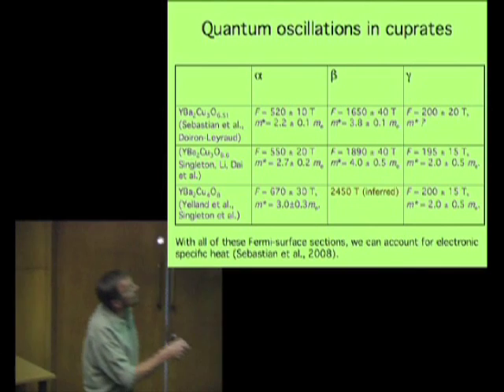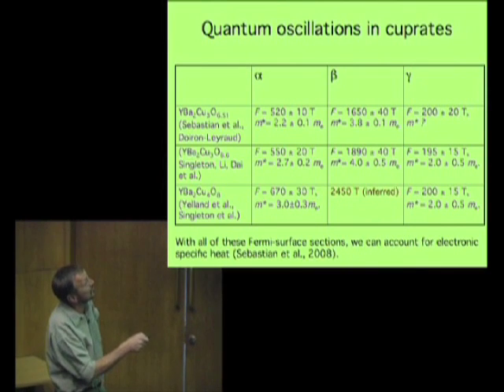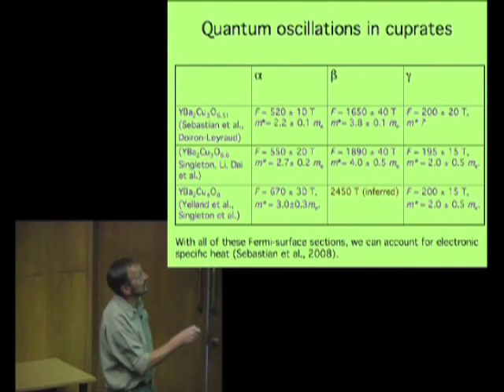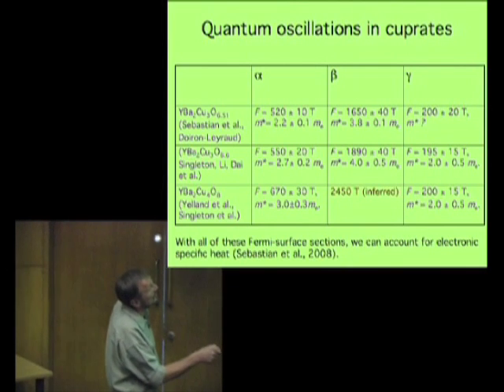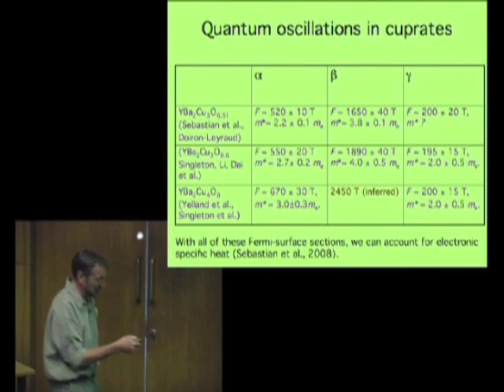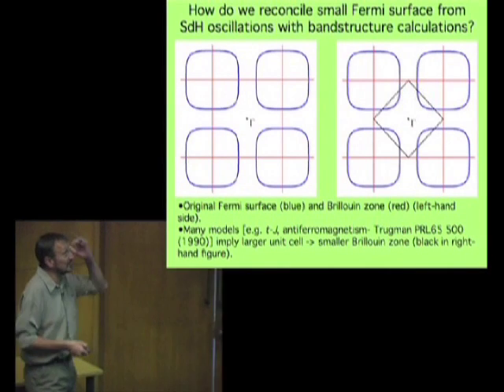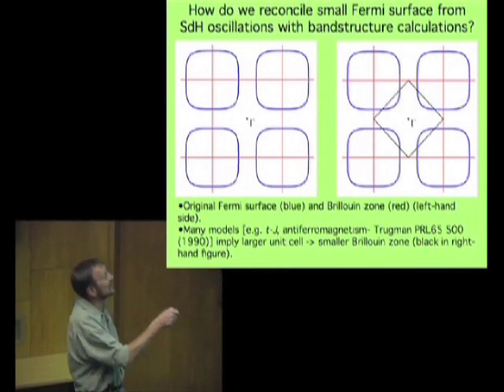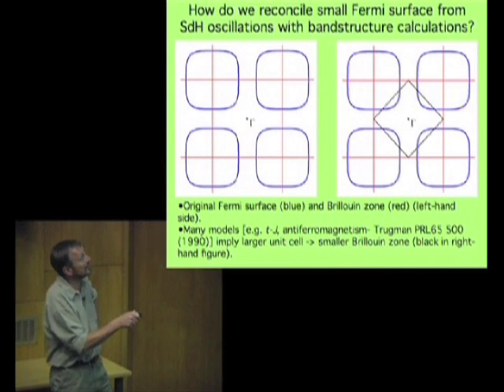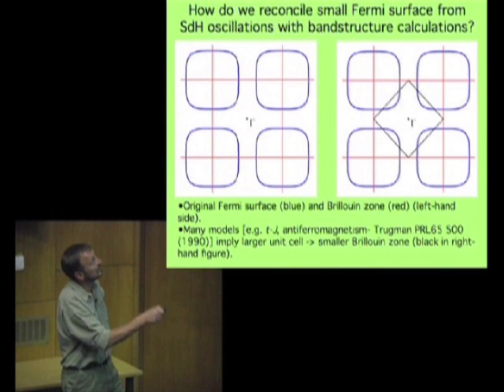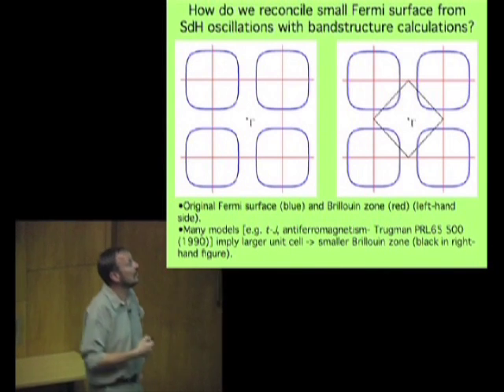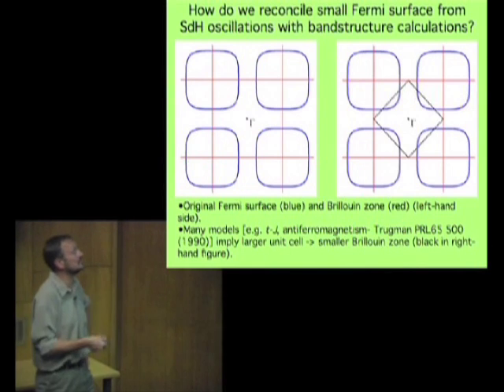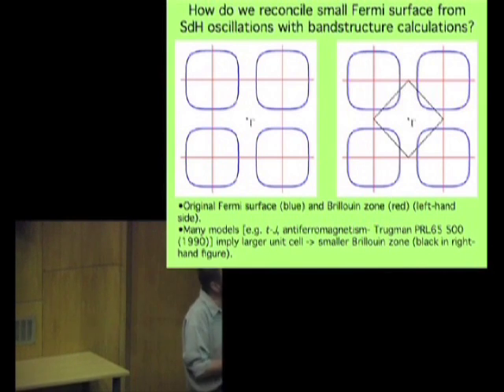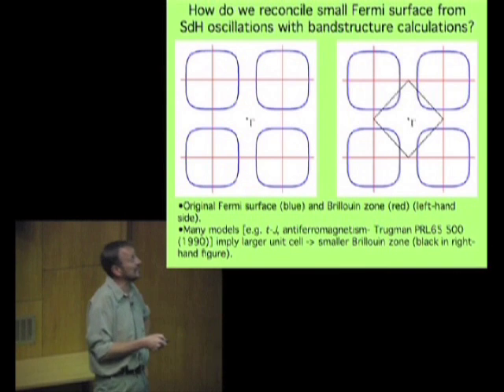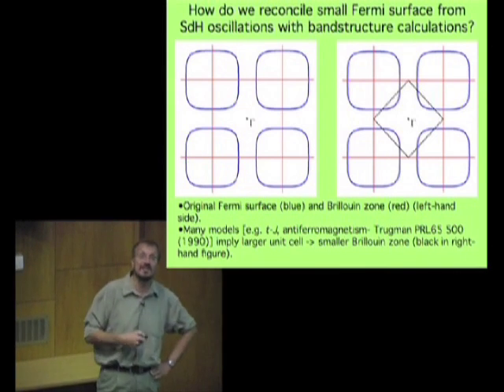So you will remember that when I first mentioned these things, they correspond to a few percent of the Brillouin zone, a few percent of the unit cell cross-section in K-space. This is about 2.7%, this is about 6%, about 7%, 8 or 9%. So how does this compare to the calculated Fermi surface? Well, this is the original calculation of the Fermi surface. Very simple thing, approximately square. This is the unit cell of K-space here. So what's happening to produce these much smaller Fermi surface sections that we detect in the measurements? Well, what's actually happening is that there's an additional periodicity in the system.